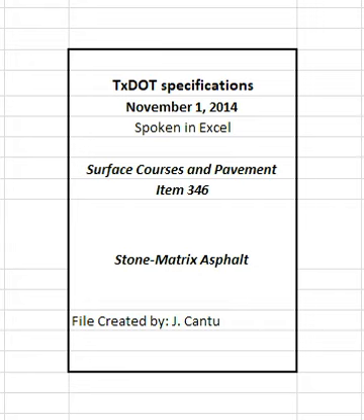Maintain the inline measuring device to verify the AR binder viscosity between 2,500 and 4,000 centipoise at 350 degrees Fahrenheit when AR binder is specified unless otherwise approved. Record AR binder viscosity at least once an hour and provide the engineer with a daily summary unless otherwise directed.